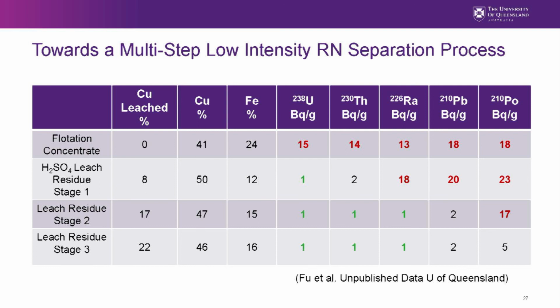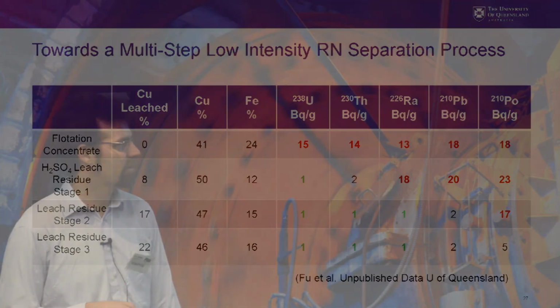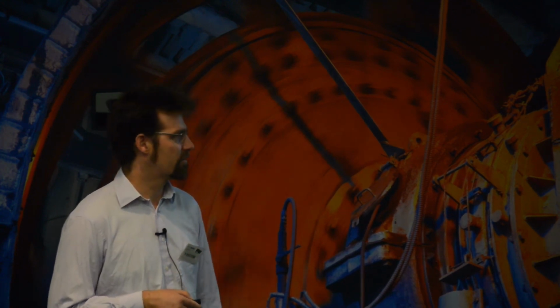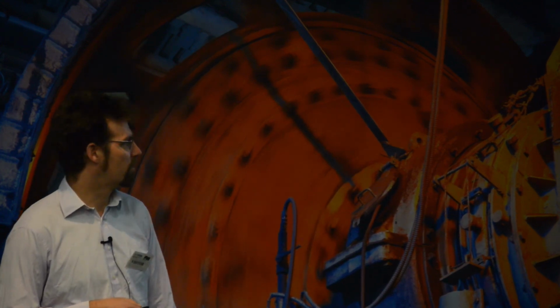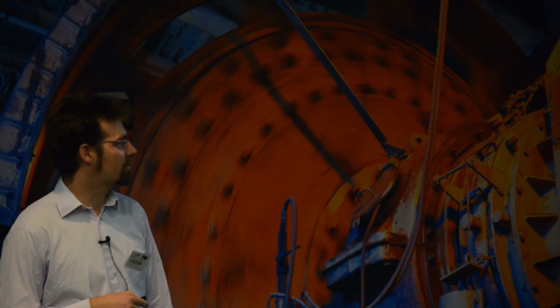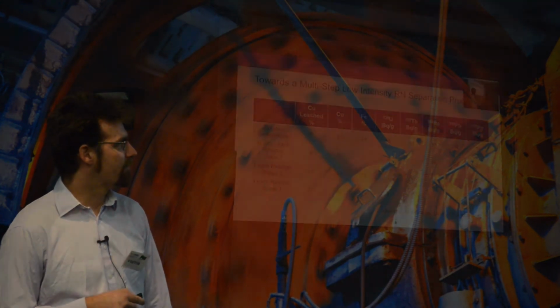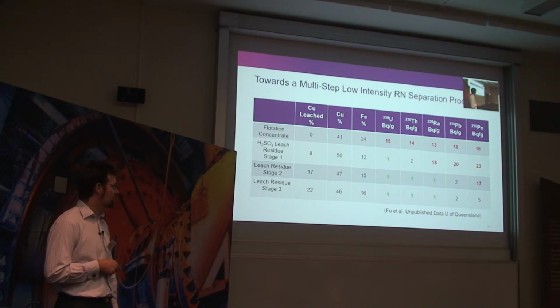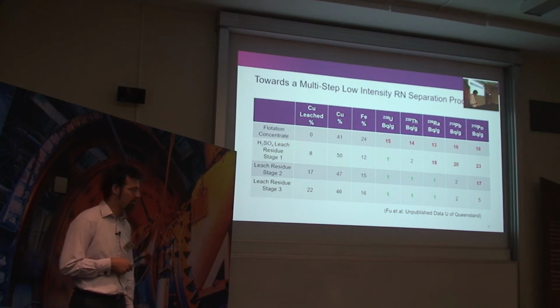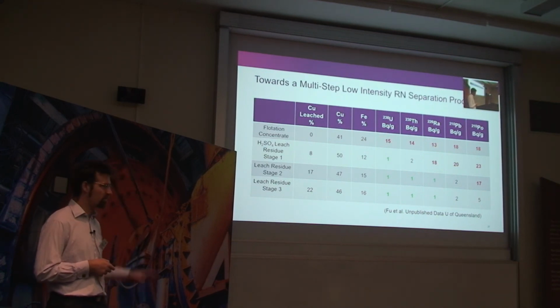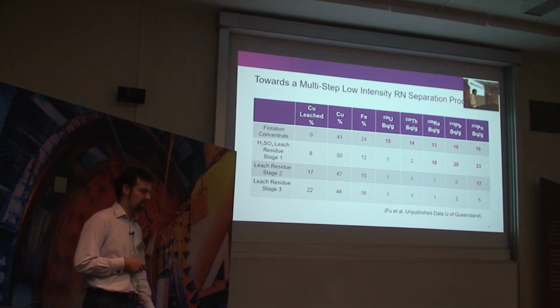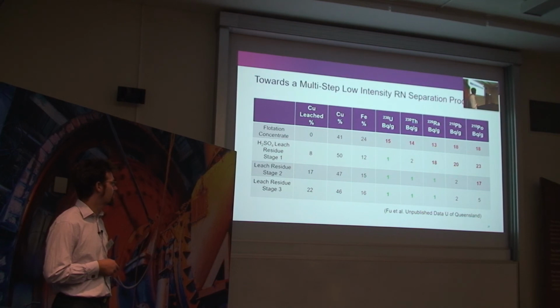One is the objective, so we've got to one for 3 out of 5 elements here after this process, and we're still working this year on trying to get these numbers down to get ones across the board. At the same time, we're trying to minimize the copper leach as a general rule of thumb. And in this case, after the three steps, we still do have 22% of the copper solubilized. So these are some preliminary results, and we're hoping to share more details about that by the end of the year.